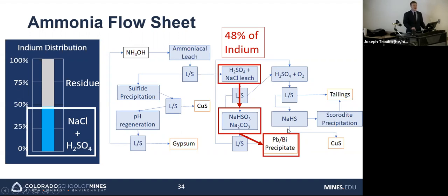Sodium carbonate as opposed to calcium carbonate is used here to prevent calcium from forming gypsum. For those of you unfamiliar, when calcium reacts with sulfate, it forms a relatively insoluble species, gypsum, which is a good way for removing sulfate, but in this case, we don't want to dilute a potential product. To reiterate, that 48% of indium is expected to precipitate along with lead and bismuth, creating an outflow for the indium present.